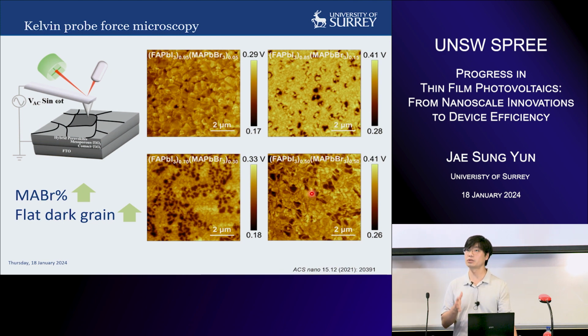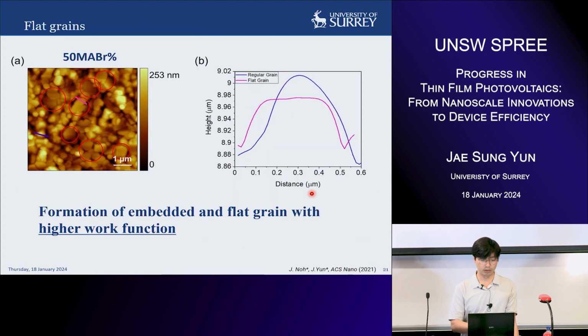So this is measured under the dark, and we can see that there is a very non-uniform structural homogeneity. These grains with a different work function happen to have a very different morphology. If you see this AFM image, these grains are very flat and kind of embedded into the film depth. And if you see the height profile, the regular grain has a valley shape. It's a very typical structure of a grain in perovskite, whereas these abnormal grains have a very flat nature in the middle.